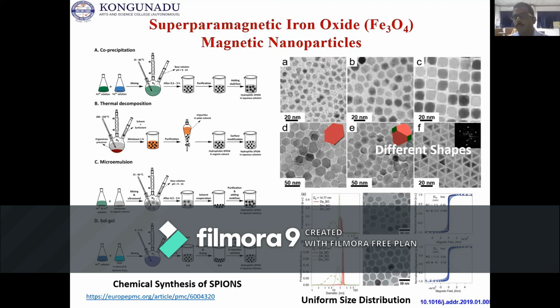ferromagnetism, which is exhibited by nanoparticles of size above 30 nanometers. So you want to restrict the particle size below 30 nanometers, and you want to have a uniform size distribution also. Otherwise, you will get this ferromagnetic loop, which will be a problem for medical applications.